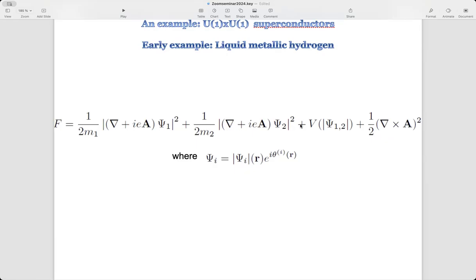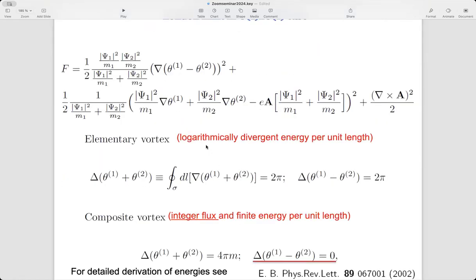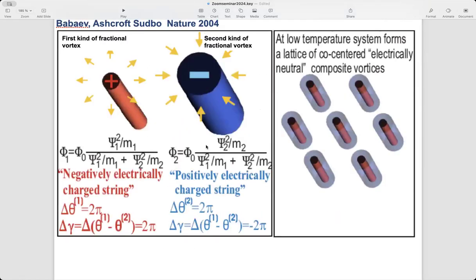But now, if one has two components and only one phase gradient and tries to compensate this phase gradient by enclosing one flux quantum, the vector potential will also appear in this other term and will make this term logarithmically divergent. So this is basically a frustration, where the system minimizes energy by fractionalizing the magnetic flux quantum. And this is what was in our Nature paper.